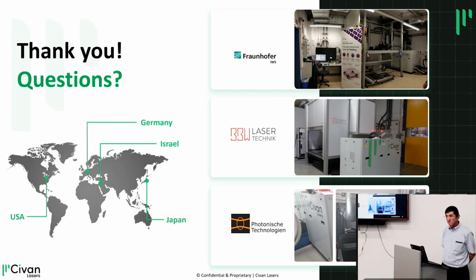Sometimes you can get spatter going through. That happens basically with the laser, and we're trying to close that gap. So that's like a blowout from the laser process. Right, exactly. That's exactly what we are avoiding. This is the process that happens many times, all these blowouts. That's the sputter that you get all over the place, and in an electrical motor, it actually creates shorts and ruins the motor. Yes, this is exactly what we are controlling to avoid these blowouts.